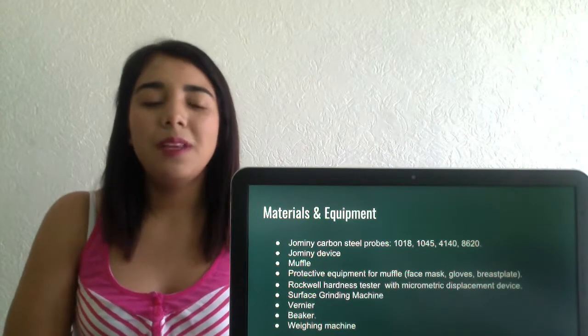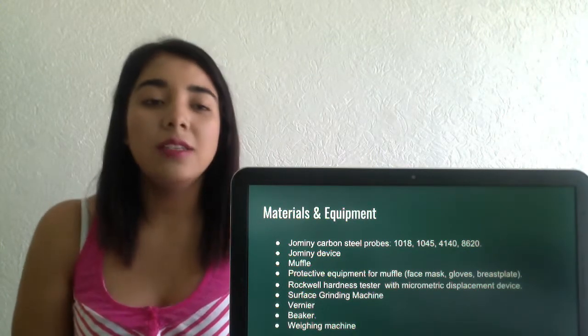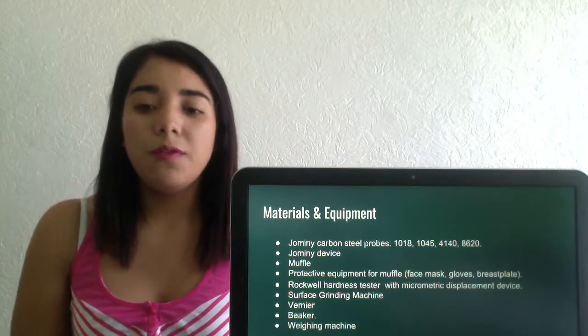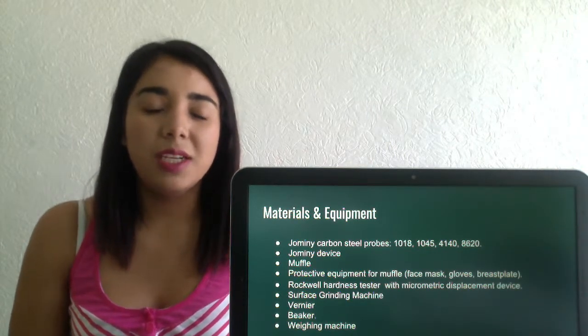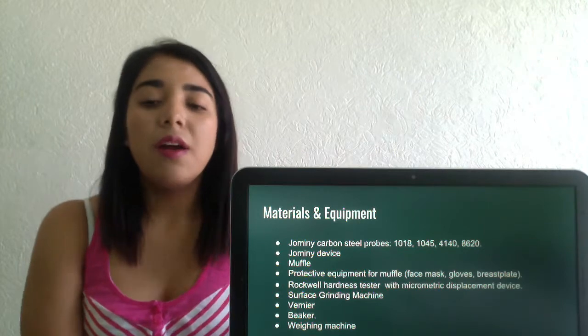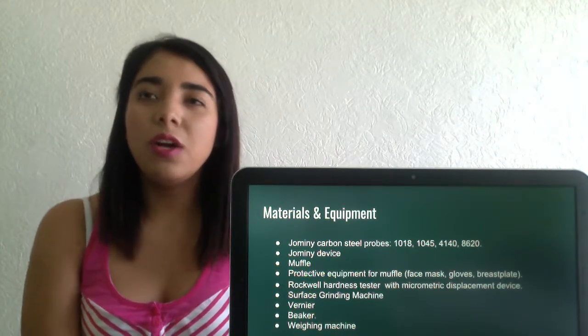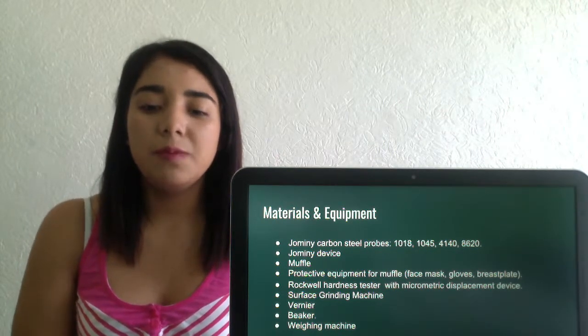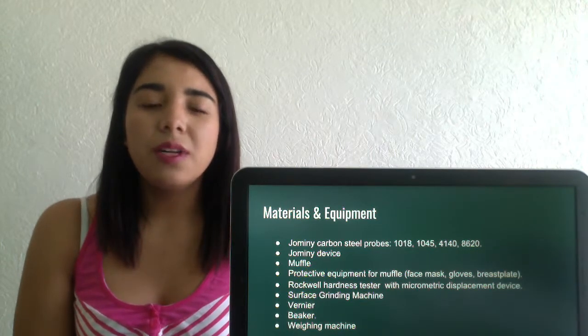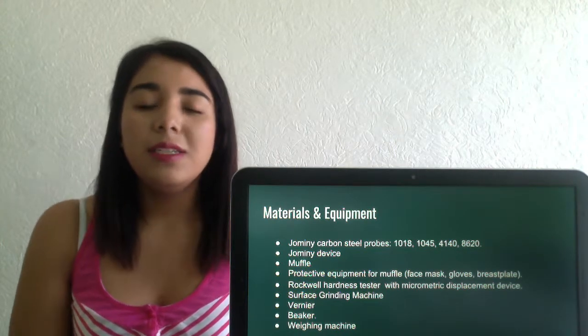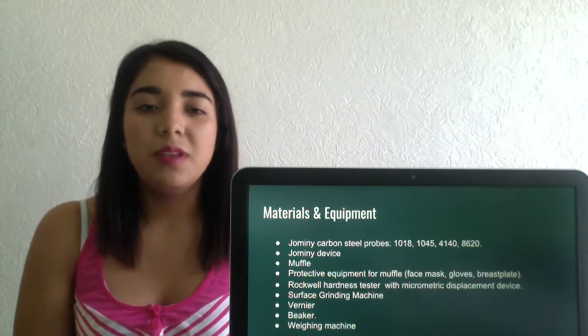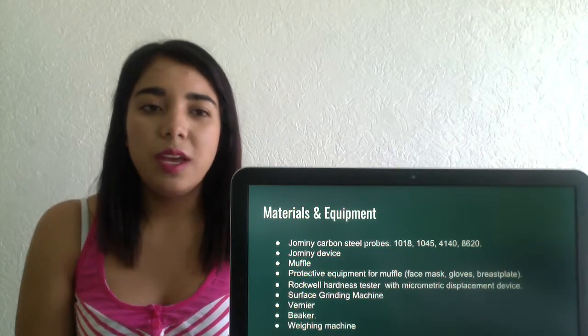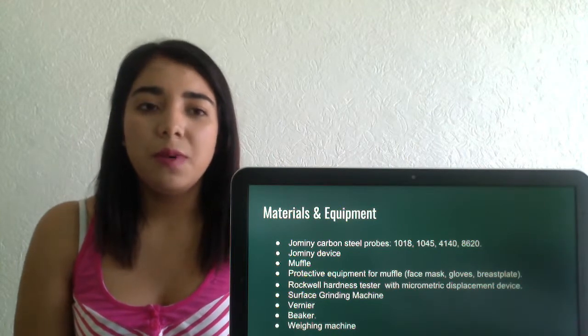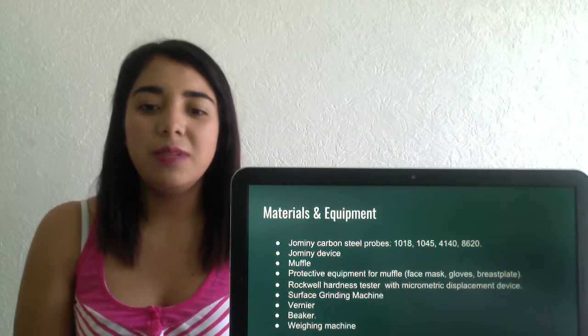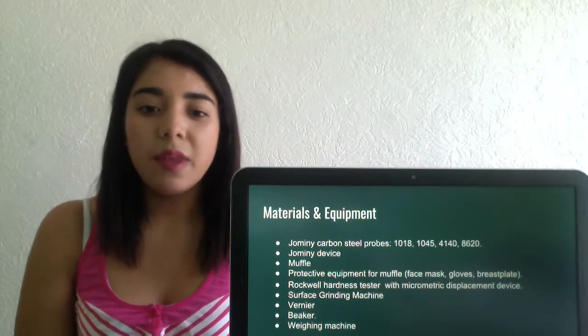In this practice, the equipment and the material that we use are the Jominy device, the muffle, and the equipment for protection: the face mask, the gloves, and the breastplate. We use the Rockwell hardness tester, and this tester must have a micrometric displacement device because we must do the test at different points. We also use the surface grinding machine, a vernier, a beaker, and a weighing machine.